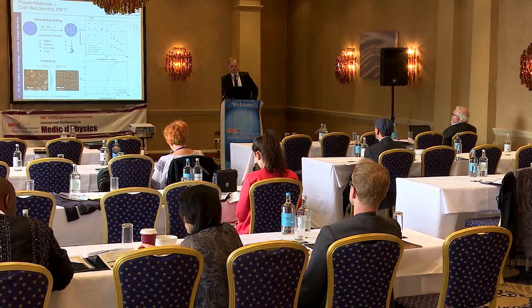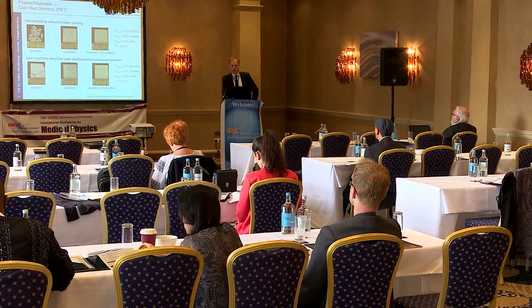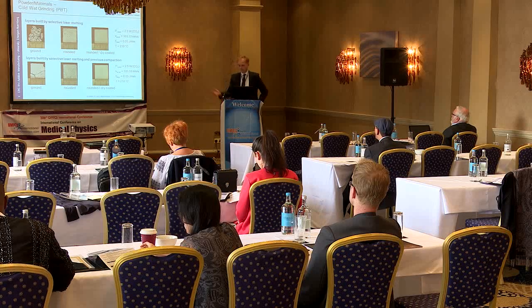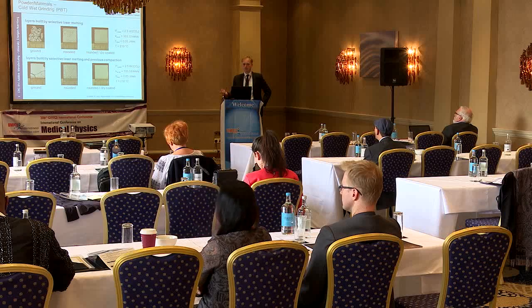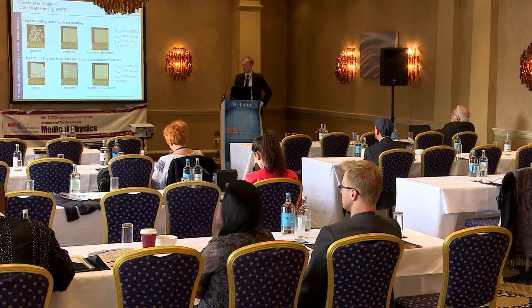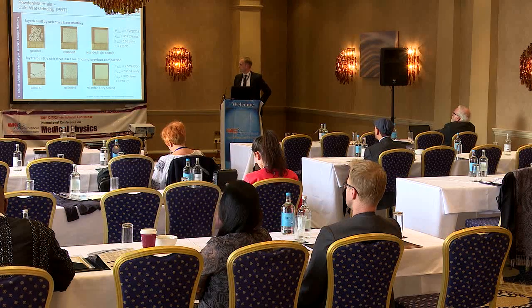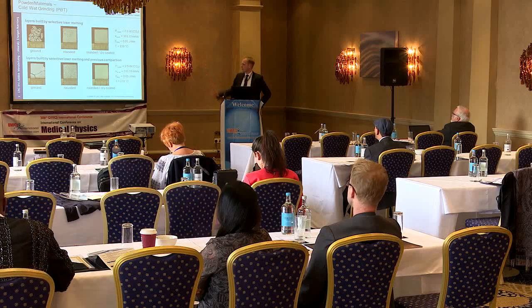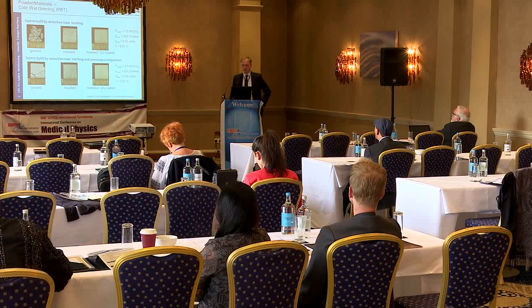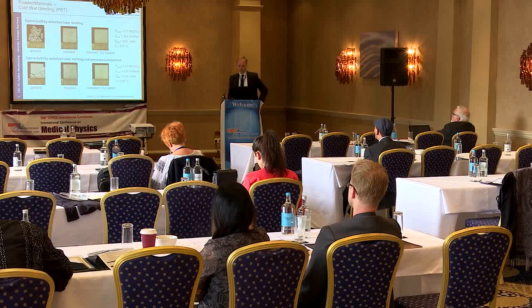But what does this mean for our produced parts? You can see this here. These are single layers molten from our produced powder, and you have this ground irregular shaped powder, and you see you don't get a closed molten state. You have a very high porosity in this layer, and it's not usable for technical applications, especially for implants.